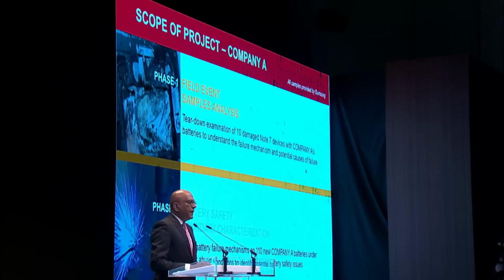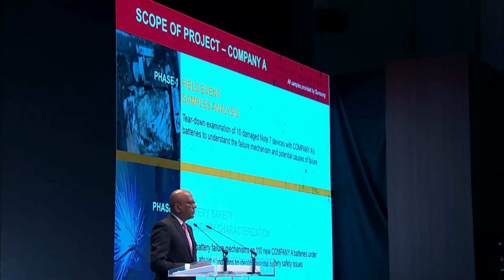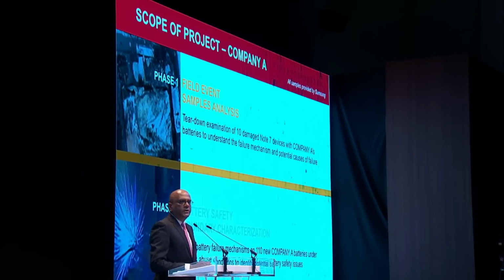fields. Engaged by Samsung and as an independent third-party testing organization, we conducted a series of tests on the Note 7 device and batteries. For Company A, we conducted 2 phases of tests. The first phase was a field event sample analysis, where we tore down and examined 10 damaged Note 7 devices to understand the failure mechanism and potential causes of failure.